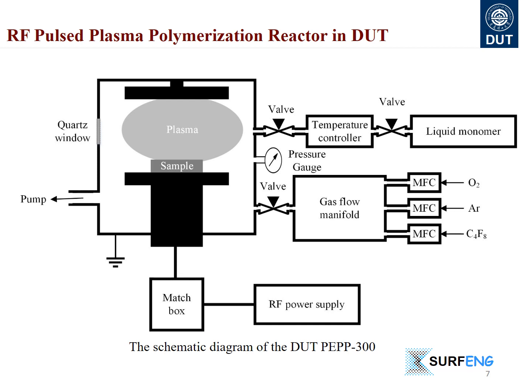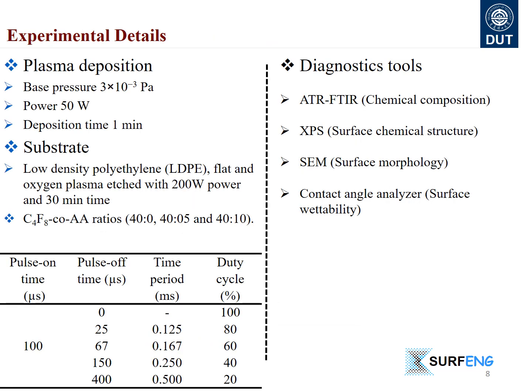Plasma etching of low-density polyethylene was performed using continuous wave mode at 200 watt power for 30 minutes in oxygen environment to produce the nano-textured low-density polyethylene surface. The RF power was 50 watt for both pulsed wave and continuous wave plasma. For pulse wave plasma, the pulse on time was kept constant, that is 100 microsecond, and pulse off time varied from 0 to 400 microsecond. The monomers were dosed with a constant octafluorocyclobutane flow rate of 40 standard cubic centimeter, along with acrylic acid flow rates of 0, 5, and 10 standard cubic centimeter.